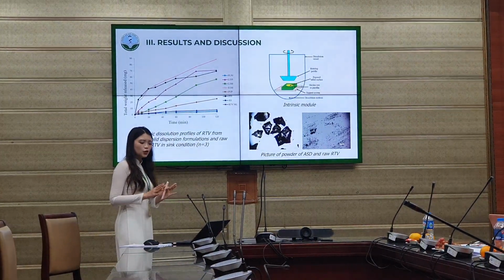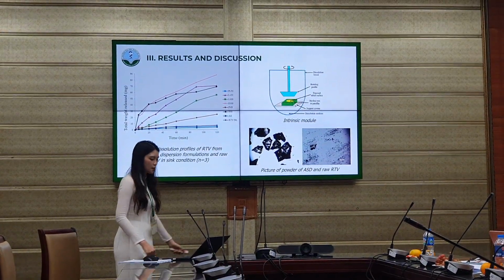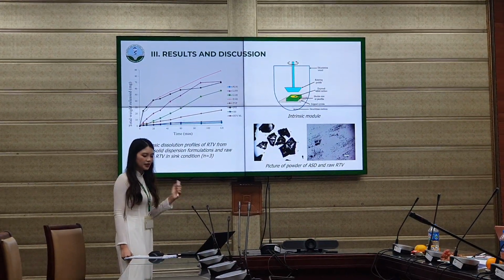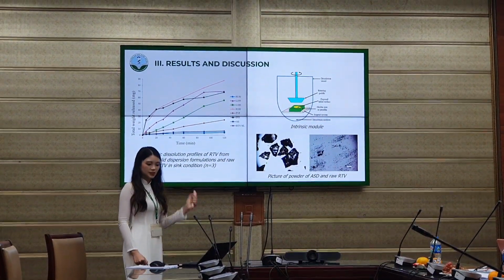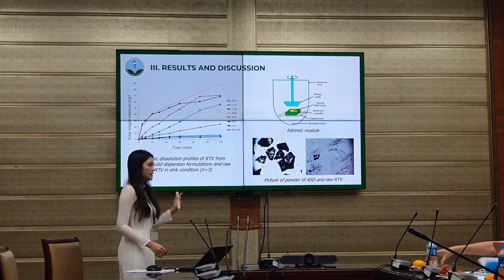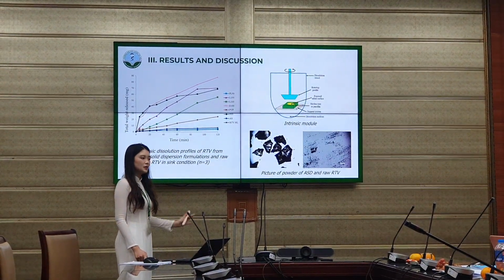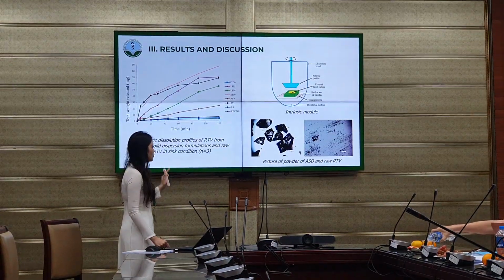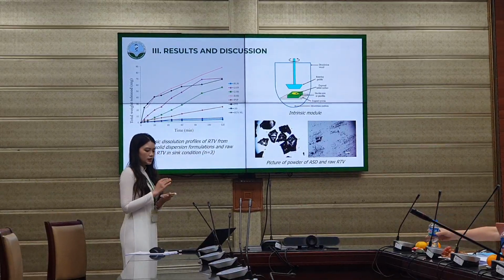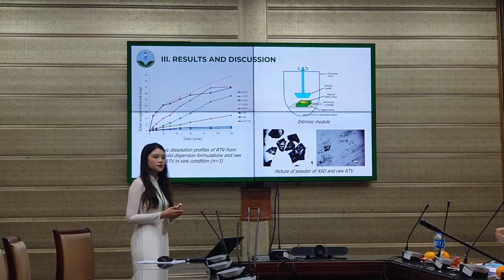Initial dissolution testing was conducted. However, when you see the pictures here, you can see that the particle size of the solid dispersion system is 0.2 to 0.8 millimeters, much bigger than that of the raw materials. So to eliminate the influence of surface area and isolate the effects of formulation, intrinsic dissolution testing was subsequently performed, and the tablet was placed in a sample holder module, like the picture, so that only one circular face was exposed to the dissolution medium, thereby eliminating the influence of surface area variability.